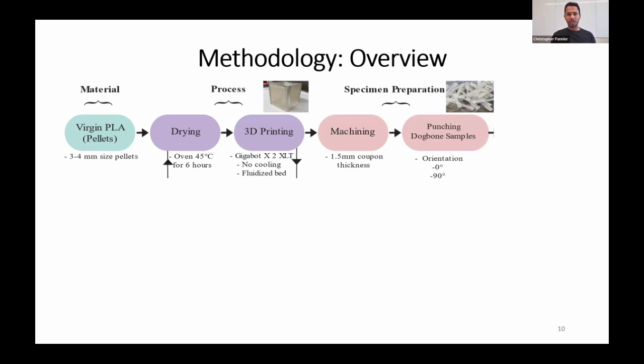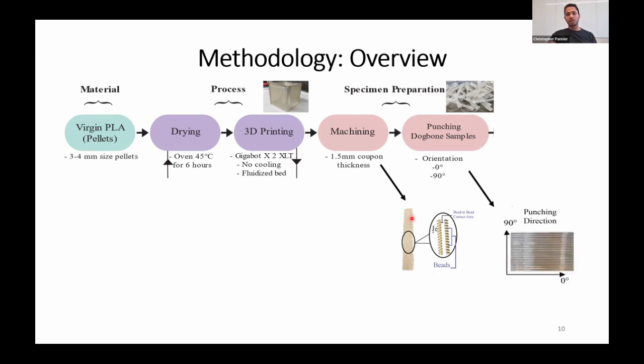So as part of the preparation, we had to cut these walls into 4 walls and machine these parts. Then we punch them into the dog bones. We did that in 2 orientations, the 0 degrees and the 90 degrees. And also we looked into the literature and we found out that if we just cut these walls and then punch them into the specimens, we would have these edges from naturally printing these walls, and they might be presented as defects. So therefore, we machined these parts.